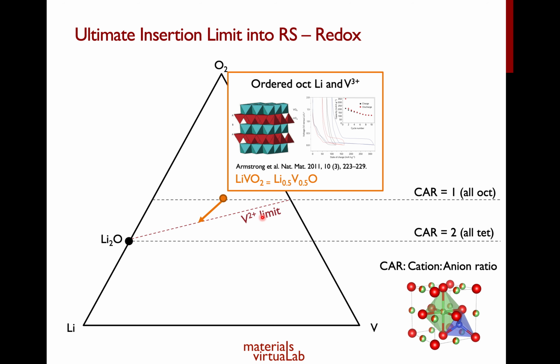So we can start from LiVO2. This is our standard layered structure. Indeed, Peter Bruce has shown that you can further lithiate LiVO2 to Li2VO2. To write this in the rock salt formula, this is Li0.5V0.5O. When you lithiate, you follow this lithiation pathway up to this position over here. Now, when you lithiate into LiVO2, you get a much lower voltage material. Peter Bruce showed this in a publication in Nature Materials: if you lithiate into VO2, your voltage is below 0.5 volt. It's fairly close to graphite. However, the rate capability and the cyclic stability are not as good as the disordered rock salt Li3V2O5.